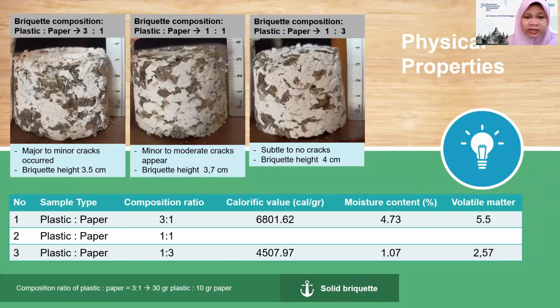For the combustion properties, there are additional parameters that have been analyzed, such as the moisture content, calorific value, and the volatile matter. It can be suggested that under high temperature heating, when the sample has been inserted into the oven, the paper will lose the water content, but plastic seems to be melted only with a lesser amount of water. It might be trapped in the chemical component of the plastic itself. Paper has the ability to absorb water, so it is possible to have high moisture content, while the density value has no correlation with the value of the water content.